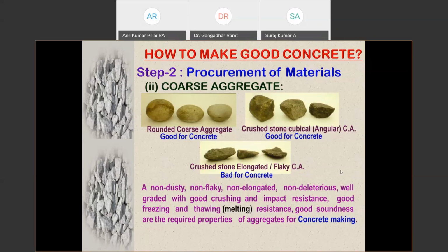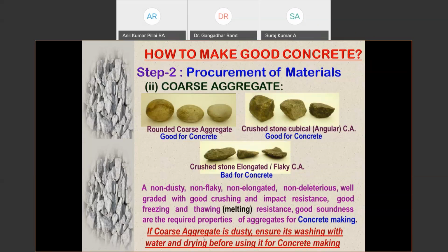Hence, if coarse aggregate is dusty, we must ensure its washing with water and drying it before using it for concrete making, because this makes a lot of difference to strength. If we compare a washed dusty coarse aggregate with an unwashed one, I can say about 50% strength remains with the dusty one, even less than that I can assure.